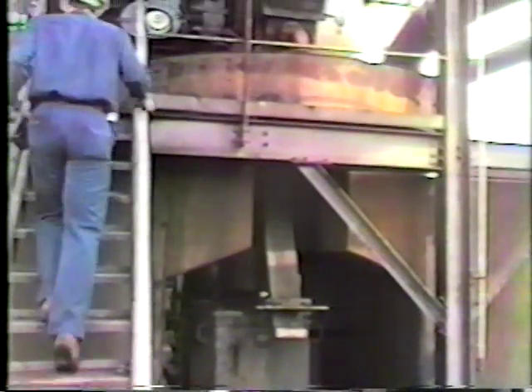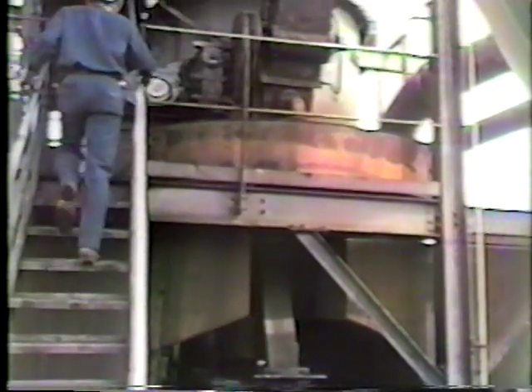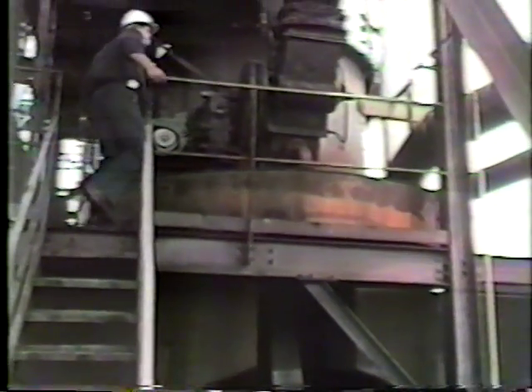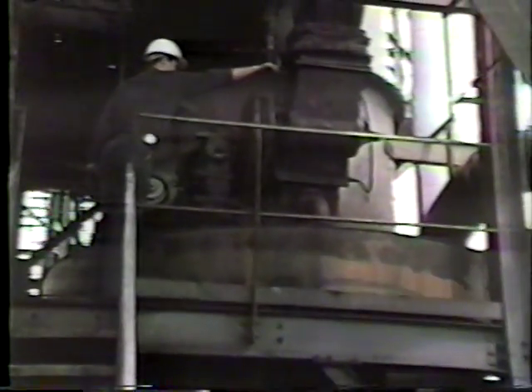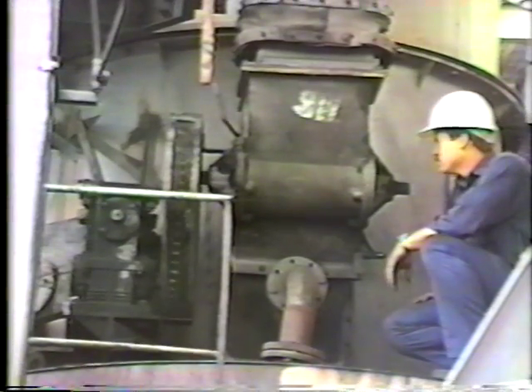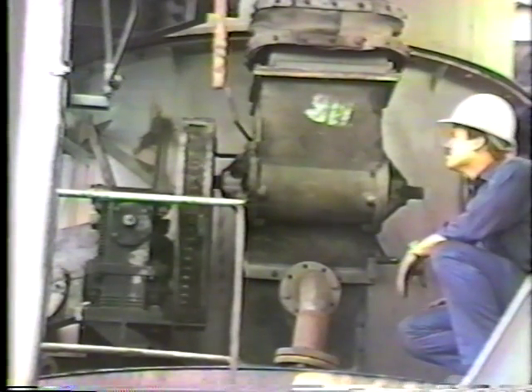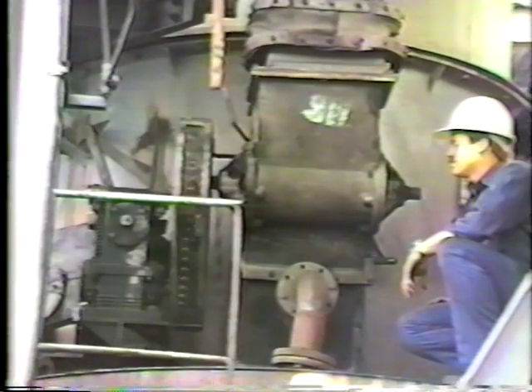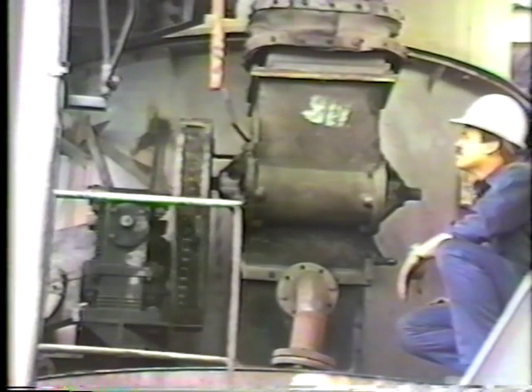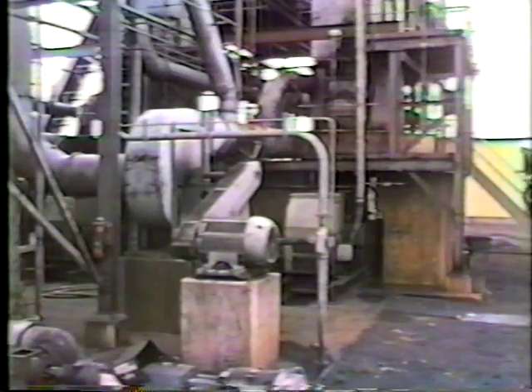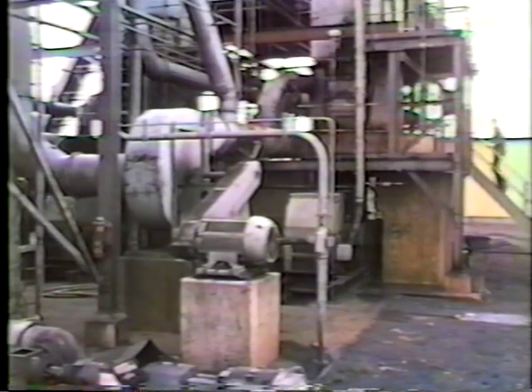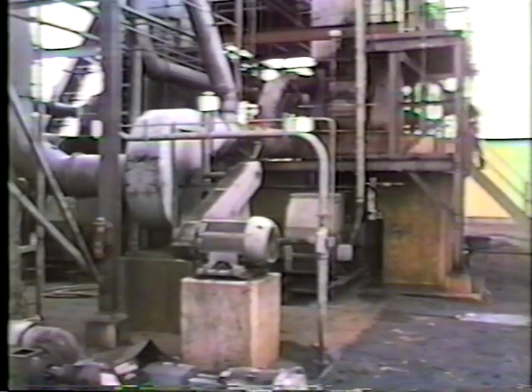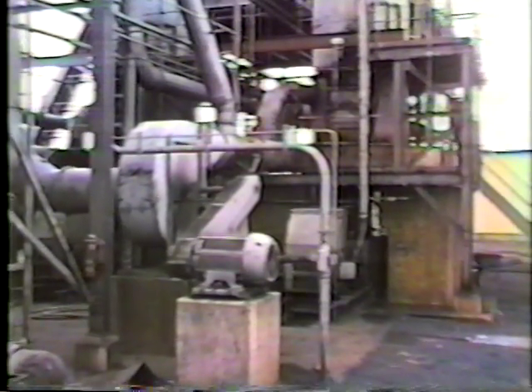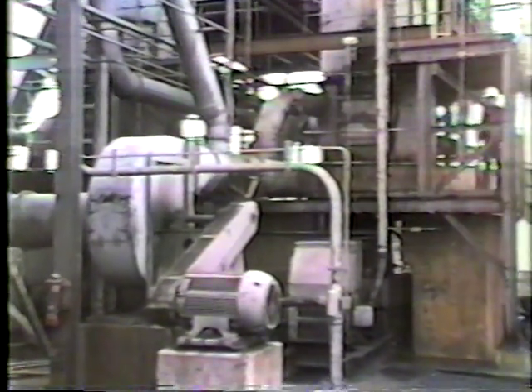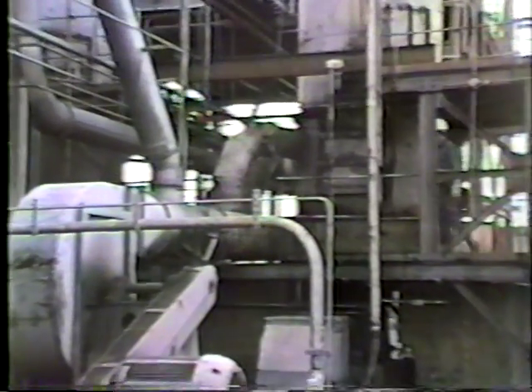Leaving the drive system, we now approach the pulverizer's airlock feeder. This feeder runs continuously and provides an even bed of coal as called for by the differential pressure controller, located by the control panel. At the same time, it prevents the egress of oxygen into the system. Processing 15 to 20 tons per hour of coal, the Williams micronizing pulverizers are grinding the coal to a fineness of 98% minus 325 mesh.